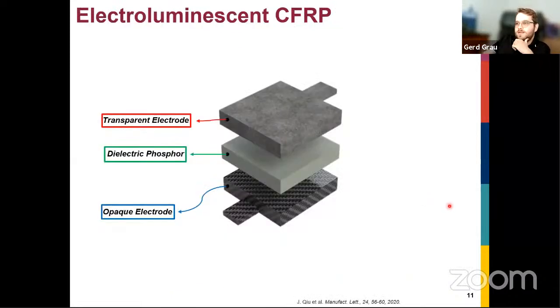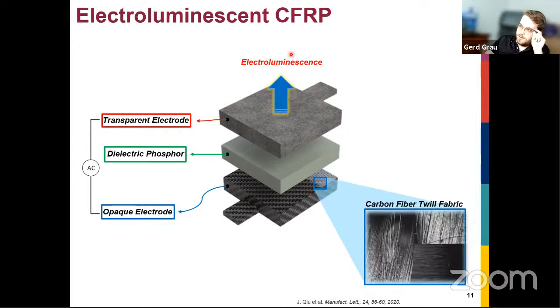So we developed this electroluminescent CFRP then, using a fairly simple structure, a capacitive structure with 2 electrodes and then a dielectric in between. And if you apply an AC voltage between your 2 electrodes, the dielectric phosphor will emit light, and it goes through this transparent or semi-transparent electrode here. So electroluminescence, of course, is not a new principle, but we showed here that you can do this with a carbon fiber compatible manufacturing process.